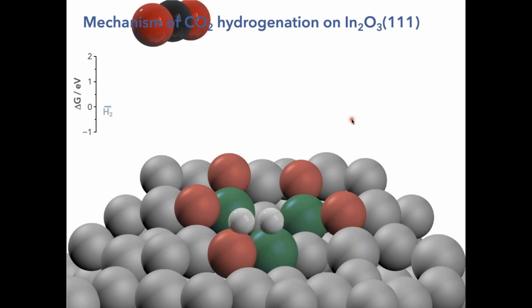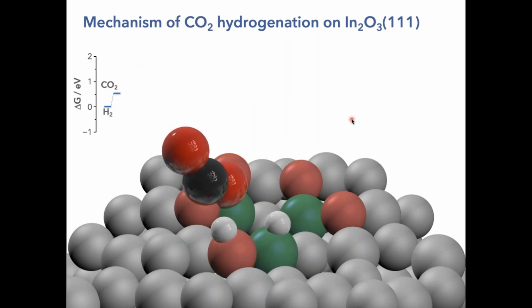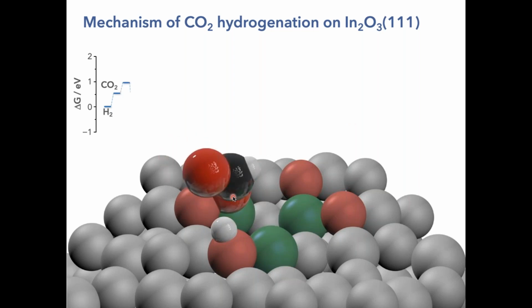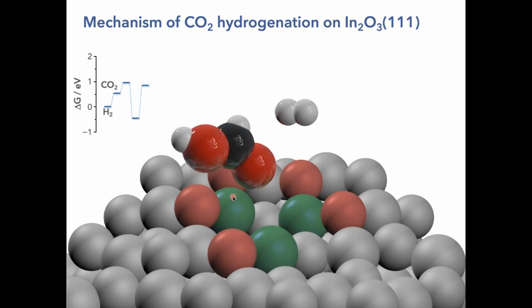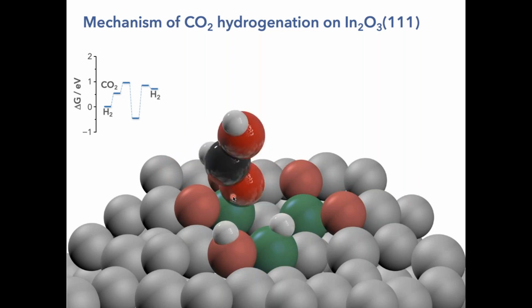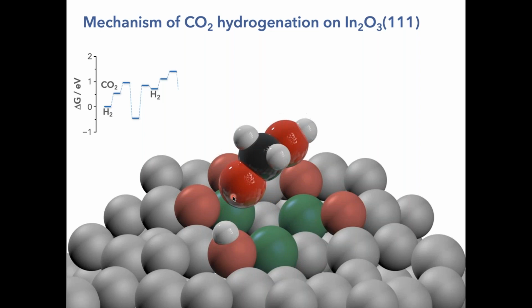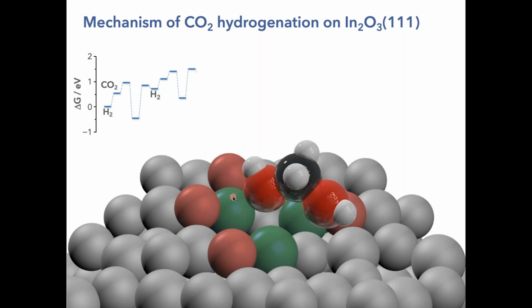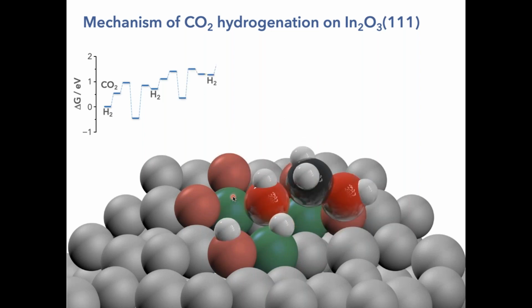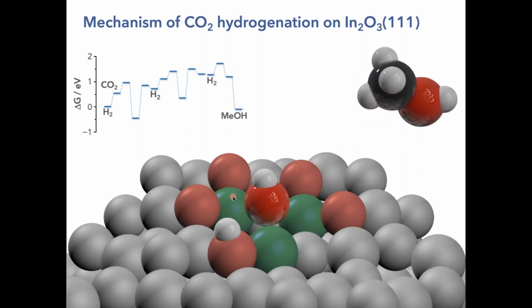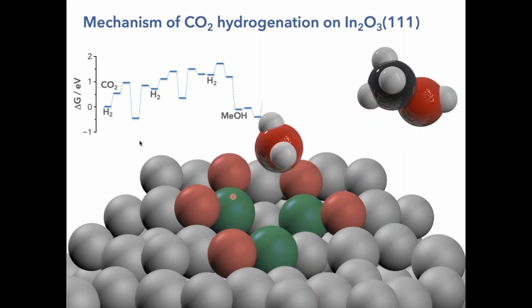So this shows you the DFT image computed by my colleague Núria López at ICIQ of the reaction where you have hydrogen activation and CO2 activation, and then the sequential addition of 3 moles of hydrogen to the CO2 molecule, producing a whole series of intermediates until the gas phase methanol is produced. And this is the energy profile.